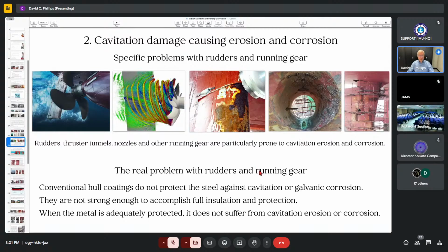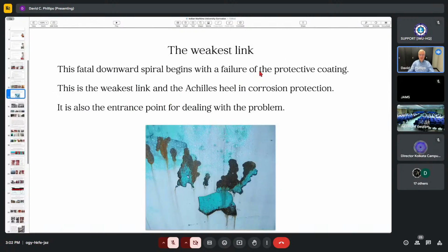So, conventional hull coatings, what normally happens is, they'll just put the regular hull coating on here. It doesn't protect it at all. It just is not up to it. Again, I'll show you another couple of examples of how that goes. But it just doesn't protect the steel. The coating gets taken off quite quickly, and then the underlying steel starts to get pitted with the damage. If this were adequately protected, if it could be, you would not get any of that. The coating actually would protect the steel, as we covered in the earlier point about the weakest link. The weakest link in the spiral begins with a protective coating. Well, it's no different for cavitation.